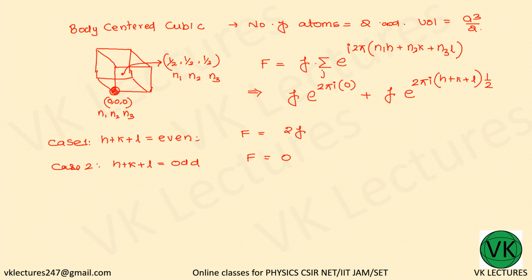So planes that have h plus k plus l value equal to even are Bragg reflected.